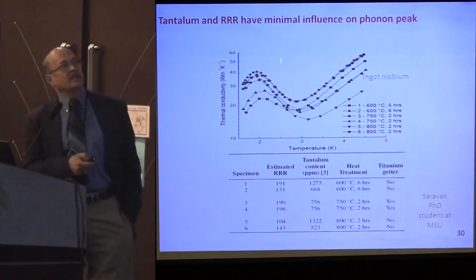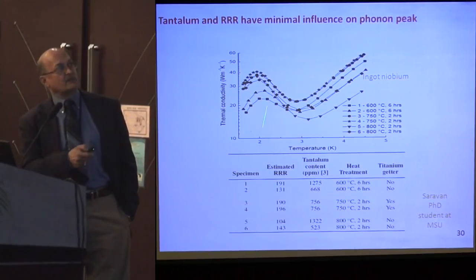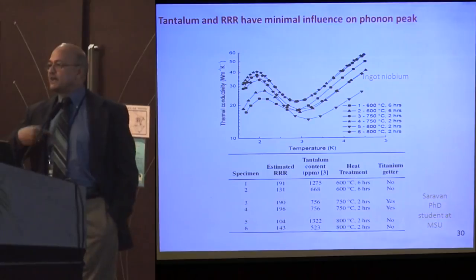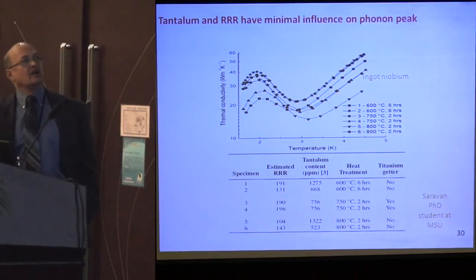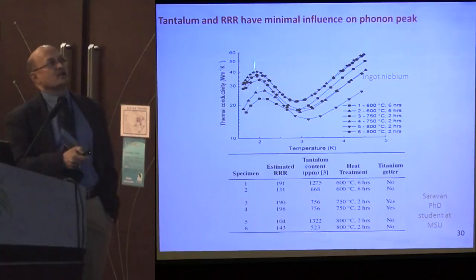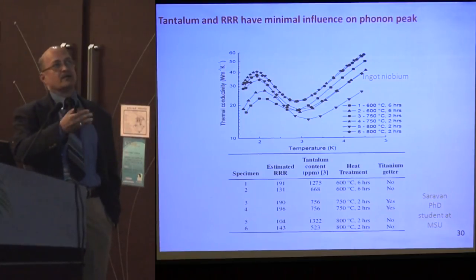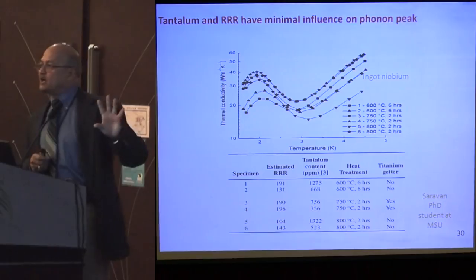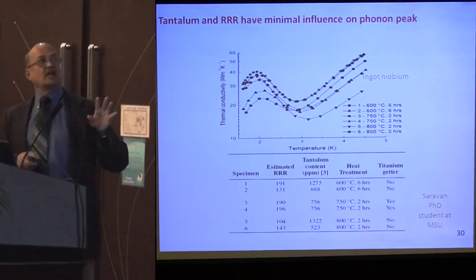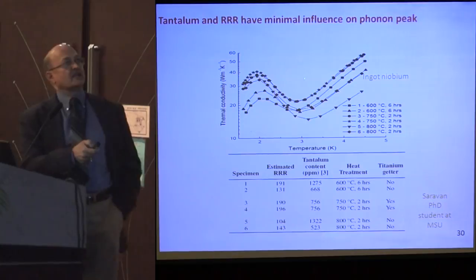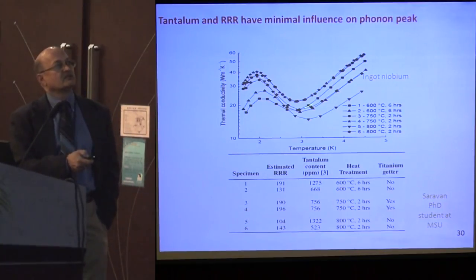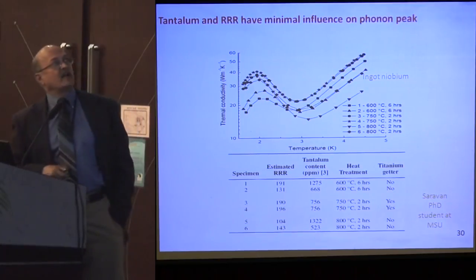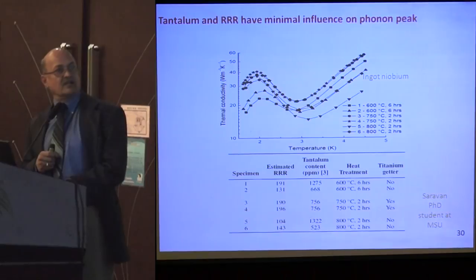Another advantage of ingot niobium material is that you have something called a phonon peak at 2K, where these accelerator cavities are operating. Even if you have some heat dissipation from surface impurities, due to this phonon peak you're able to remove that heat very effectively, which is not possible with fine-grained niobium cavities, because you don't have the phonon peak. The thermal conductivity of fine-grained cavities will go down somewhere here. So there is at least a factor of 2 to 3 higher thermal conductivity in ingot niobium.